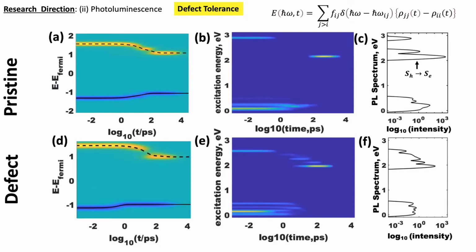So by bringing in this time of recombination, one can, maybe not very precisely, but from first principles, in one pot, in all calculations coming from the same stem and without additional approximations, assess the photoluminescence quantum yield. So this integration over the time range brings all probabilities to emit light at different instants of time together and generates the spectrum.